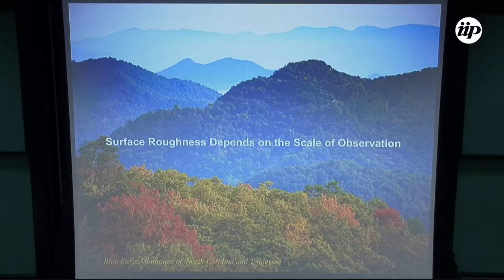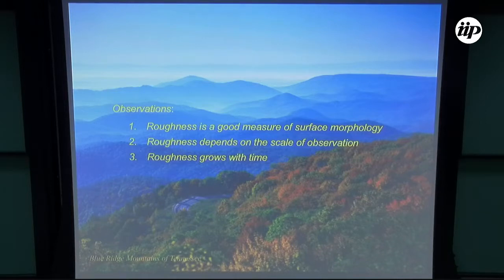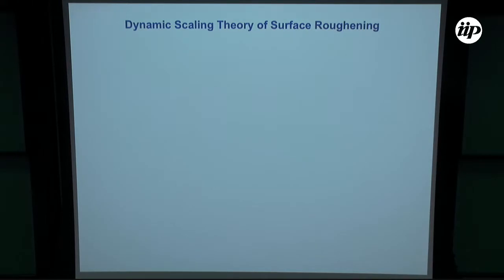So overall, we have three observations. I want to repeat them again because they're important. That roughness is a good measure of surface morphology. You look at these surfaces, that's not bad to say that this has a certain roughness, this is a different roughness. In thin film growth, and of course in any kind of surface, roughness depends on the scale of observation. But most importantly in thin film growth, because we are interested in evolution of the morphology, we notice that surface roughness grows with time. That's what we saw in the STM experiment. So how can we combine these two?